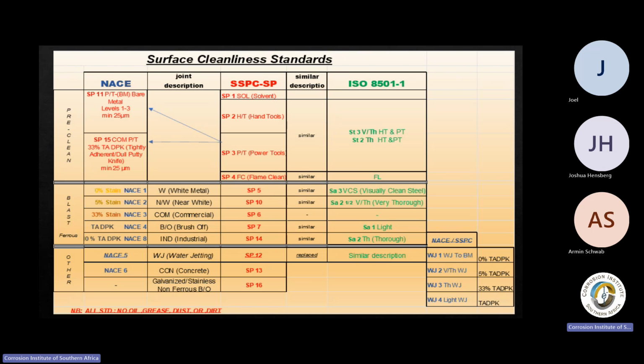So with a sandblasted surface and rain, how do you paint? The problem with rain is what did it catch going down? You can have severe contamination of sulfur, sulfur and nitrate deposits in rain, and obviously down by the coast, chlorides. So when it rains, you've got to test your surface. Once you've done a soluble salts test, testing for chloride, sulfates, and nitrates, and there's no rust back that you can wipe off, most of the time you'll have the guys let it rain. When it's done, clean off the water and do flash drops. Test again and put your coating. So that's one effective way.